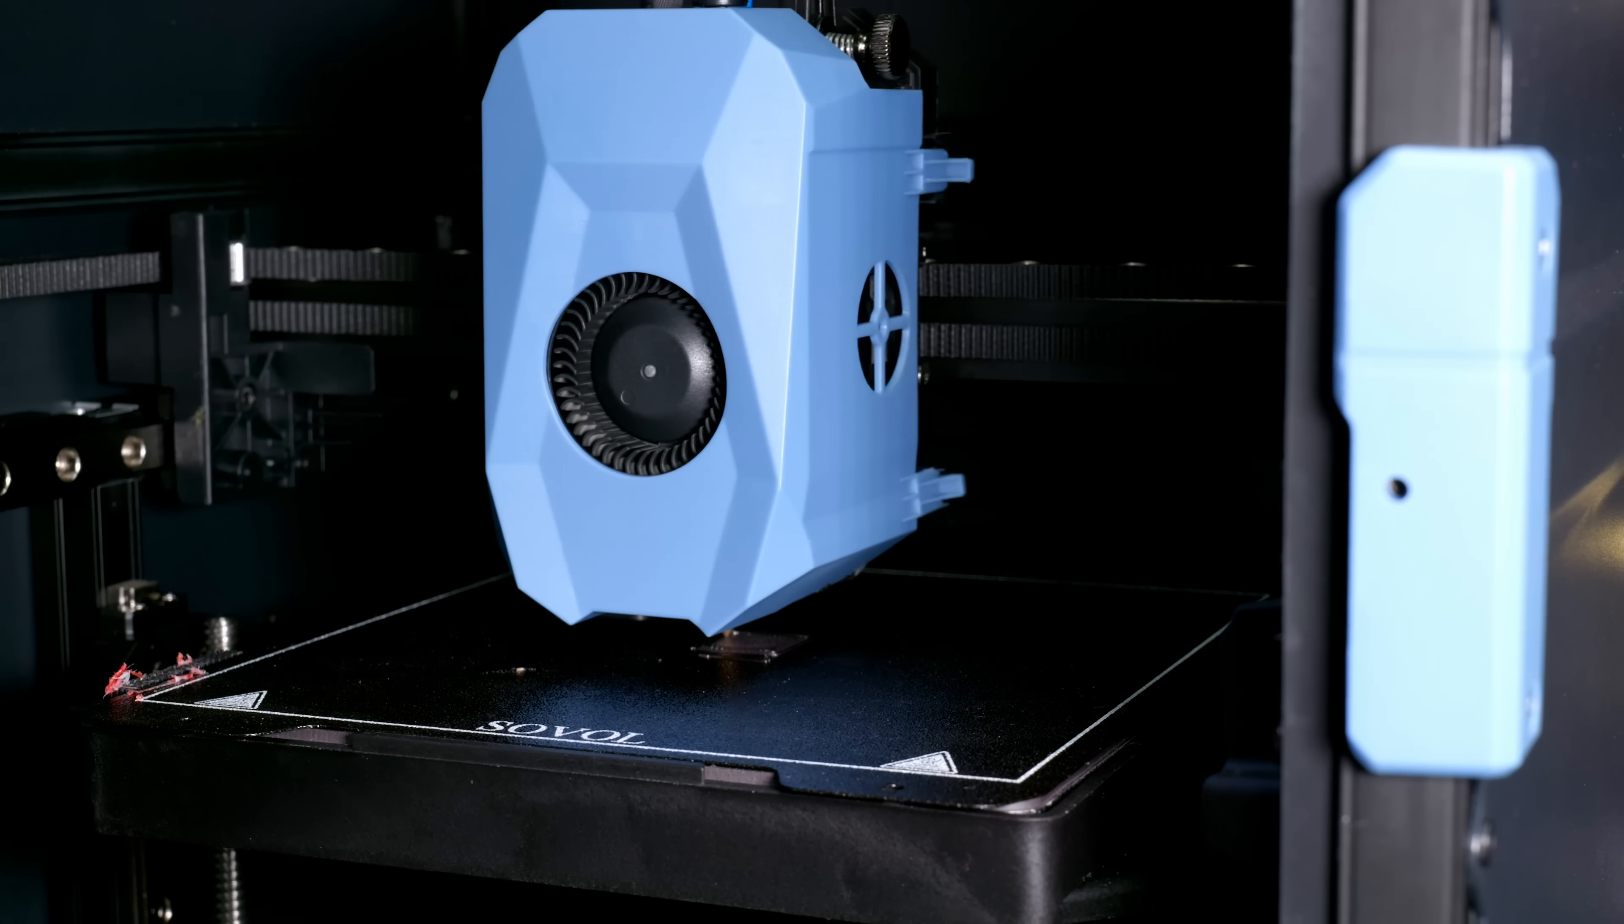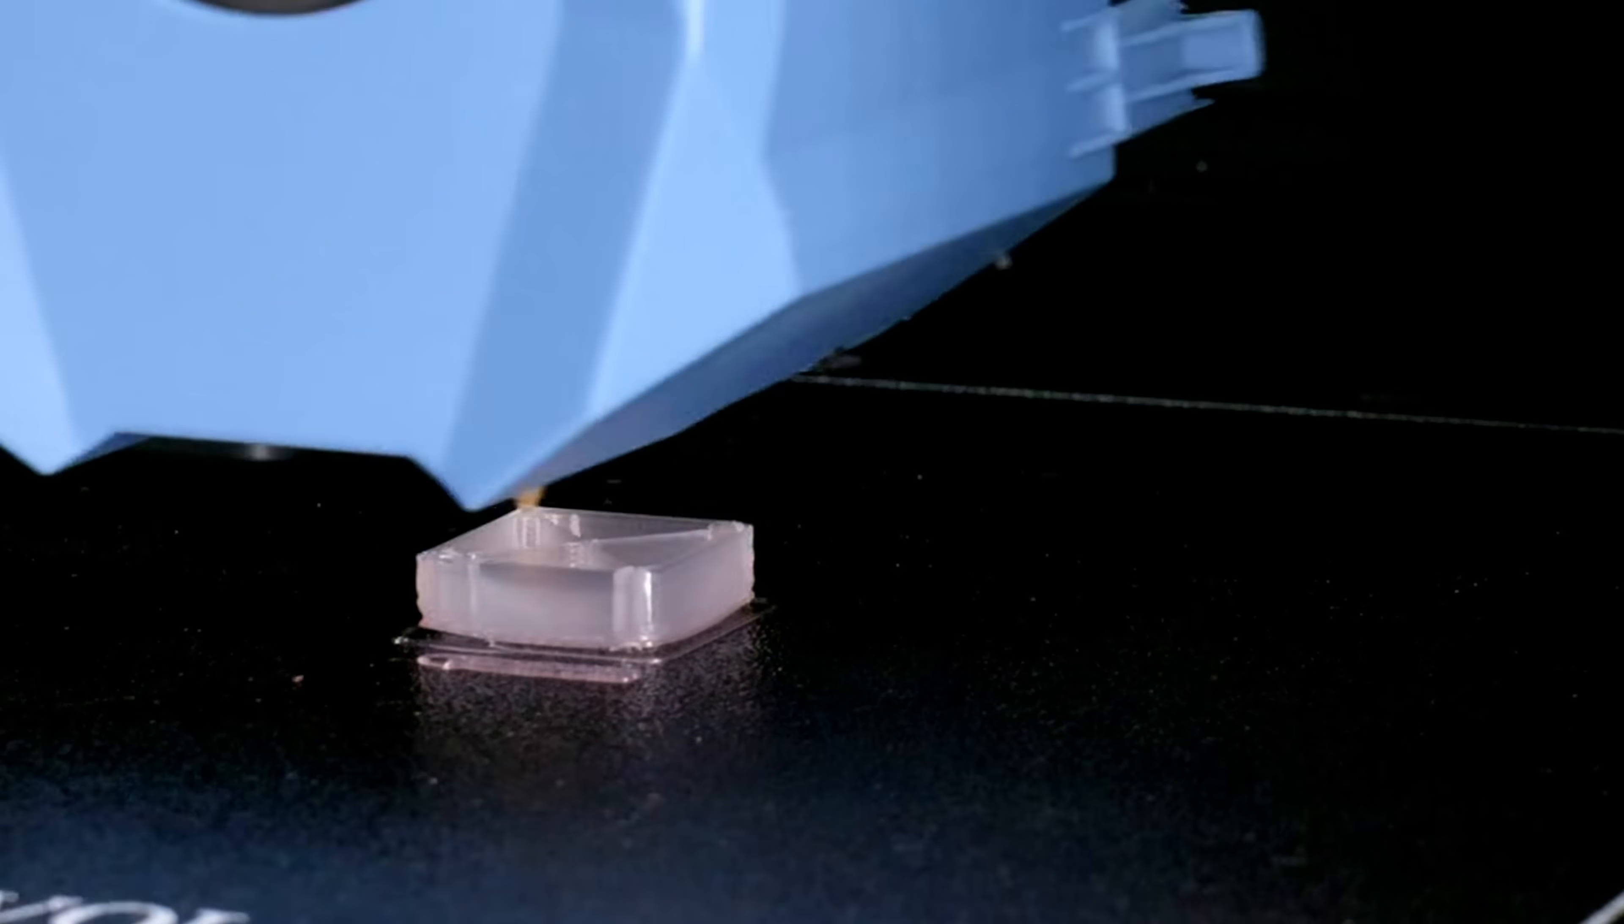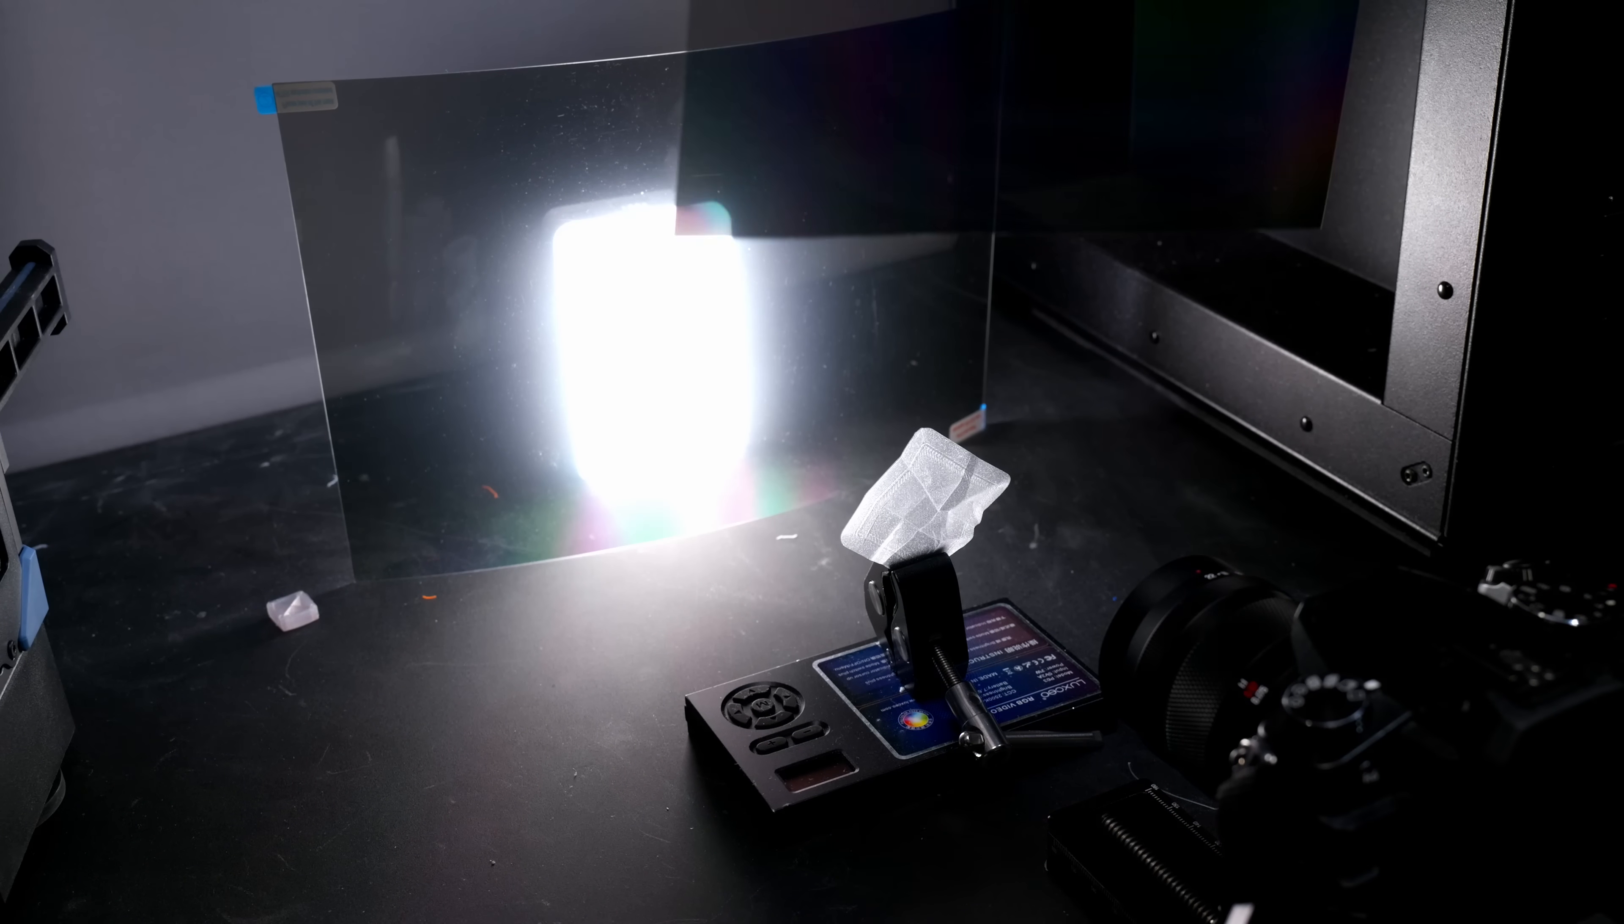Anyway, as polypropylene cools the polymer chains will begin to organise into a more ordered crystalline structure, this process causes a significant amount of shrinkage. I'm totally not reading that off wikipedia, the first layer that's laid down adheres to the print bed but then as subsequent layers are added and cooled they are shrinking and that is causing the whole thing to curl up so much more than normal. It is not the only plastic to have a semi crystalline structure but it is the only one that I've got in front of a polarised light source right now that also happens to be somewhat transparent.